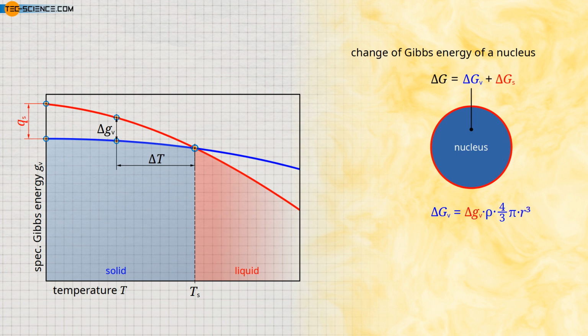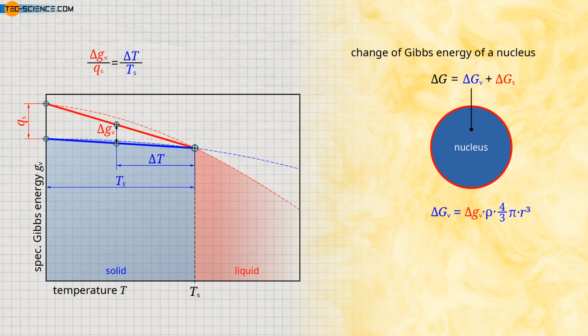Furthermore, it can be seen that the change in Gibbs energy is obviously influenced by the specific Gibbs energy delta GV. As is immediately evident from the diagram, this specific change in Gibbs energy depends in particular on the supercooling delta T of the nucleus. If one neglects the curvature of the Gibbs curves in the case of supercooling, the corresponding relationship can be derived by using the intercept theorem, also known as Thales's theorem. This states in this case that the ratio of the change of the specific Gibbs energy and the specific heat of solidification is equal to the ratio of the supercooling and the solidification temperature, provided that the temperature is given in the unit Kelvin. The change in the specific Gibbs energy when the solidification point is undershot is thus linked to the respective supercooling, as shown.